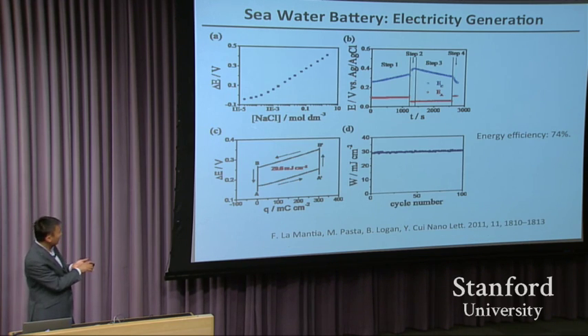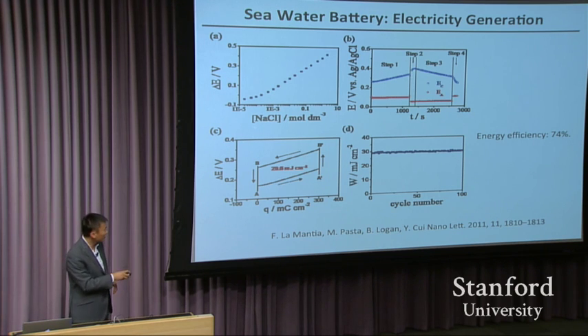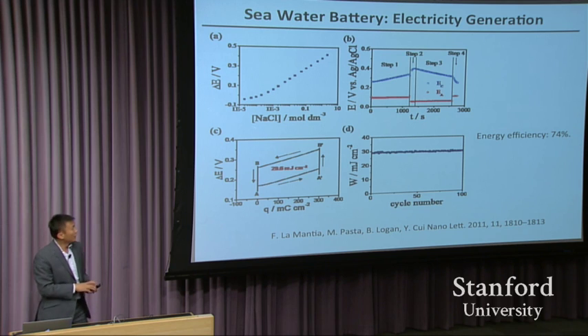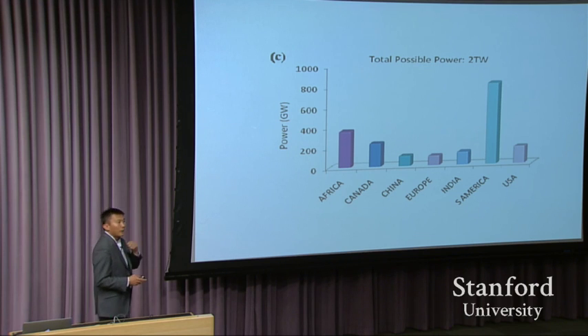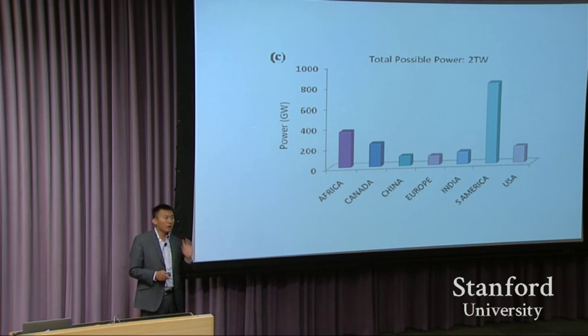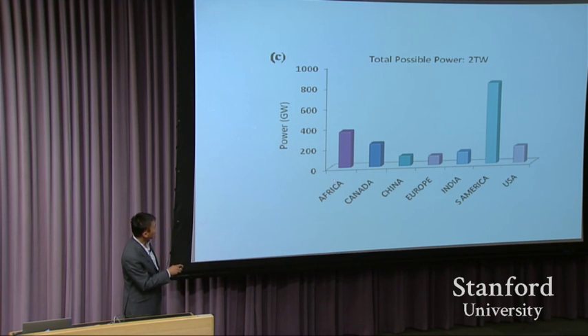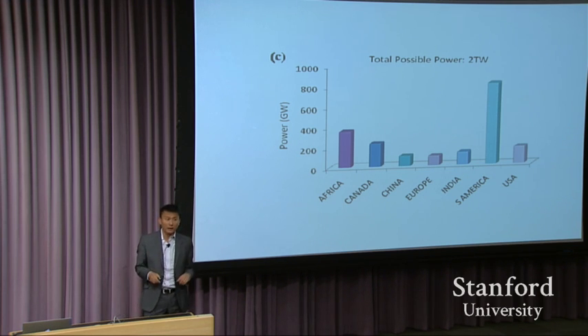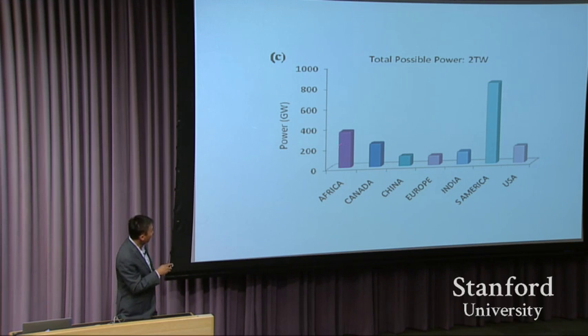So we actually experimentally measured and demonstrated a curve like this, the voltage versus the amount of charges you put in. We don't have to go into details of this curve right here. And this is the number of cycles we can do. You can do charge, discharge, charge, and discharge. This is 100 cycles, no decay, with energy efficiency of 74%. So what does this mean right here? Every year we have a lot of water going from rivers into the ocean. So you look at the distribution, South America has the most because of the Amazon River. The floods are so big right there. And Africa is quite big as well.